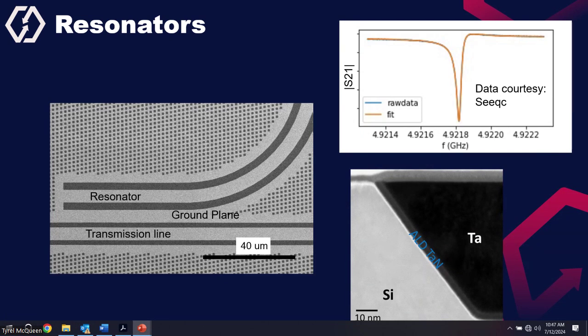So here you can see, we need ALD tantalum nitride in order to grow the alpha tantalum phase, and there is no silicon damage here at the side wall. Which, as I mentioned before, is important for quantum chips. So these are the small details that we have to take into account when we are doing fabrication for quantum devices.